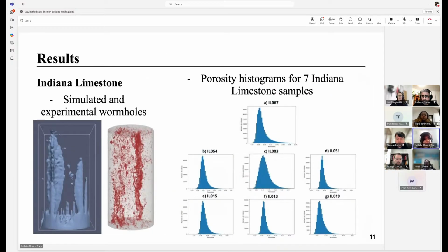Here are some of the results. I have results for Indiana limestone. The Indiana limestone is a formation known in the literature for being comparatively very homogeneous, so we don't expect large porosity contrasts in the samples. When I extract the porosity information from Indiana limestone, I get these histograms that are considerably close to a normal distribution, but it's also very close to a log normal distribution.